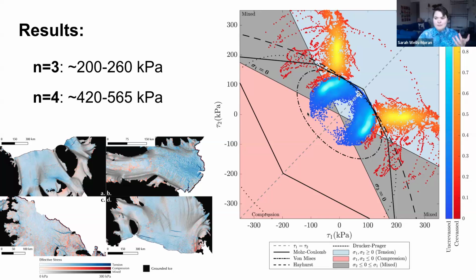And just as an intuitive method, because principal stress space was very confusing for me to figure out at first, these colors in the background plot to these colors on this graph right here. So anywhere in blue here is in tension, anywhere in gray is in a mixed regime where one principal stress is positive, one is negative, and then red is a compressive regime. And another important observation is that there are no crevasses that we observed in a compressive regime, which makes sense because the majority of these ice shelves are tensile. All of these criteria fit pretty well in the pure tensile regime. It starts to get a little bit dicey in this mixed regime. Here it appears that von Mises fits the best because it has the fewest included in this region.